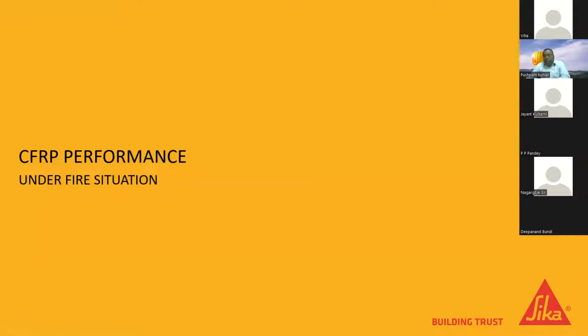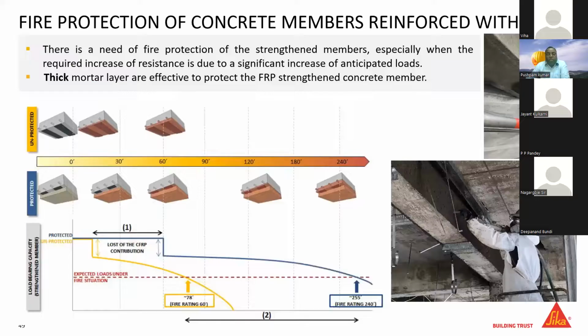So I was talking about CFRP in case of fire. Let's see, there was a test conducted wherein unprotected members were exposed to fire, and it was found that within 60 minutes, the strengthened section lost its load carrying capacity. Later, the same section was protected with fire protection mortar, and it was found that the load carrying capacity has definitely gone down, but it is still within the limit.